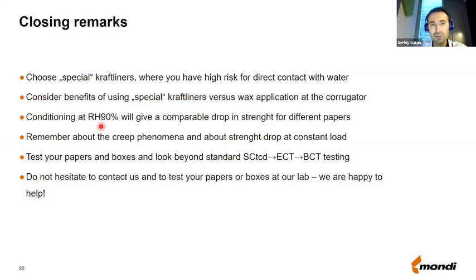Speaking about the conditioning at 90%, it is a valid test to compare the papers, but you should also remember, as I showed you earlier, that the drop in strength is quite comparable for different papers and even for different grades. Interestingly, this 50% drop in SCT values applies not only for kraftliners, which are sized papers, but also for papers made out of other raw materials like testliners, recycled papers. So it's not really specific to a type of fibers.